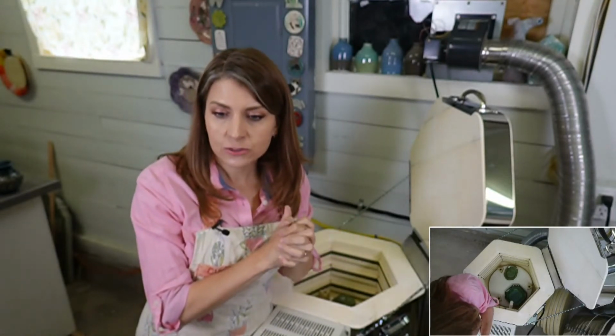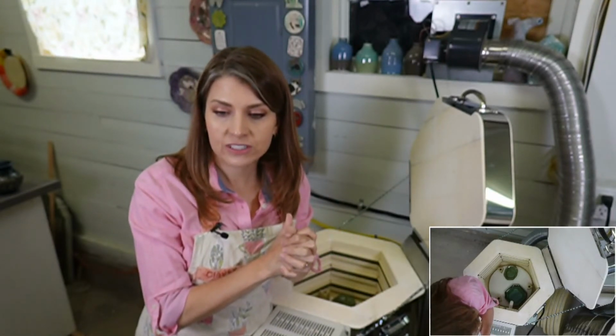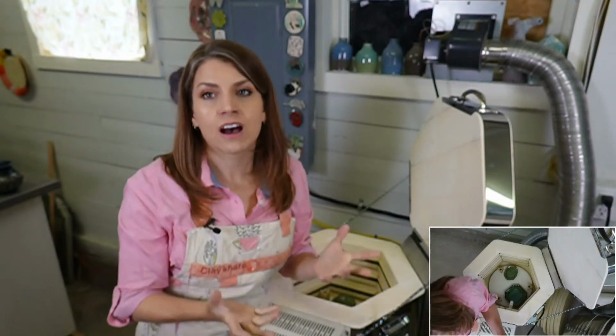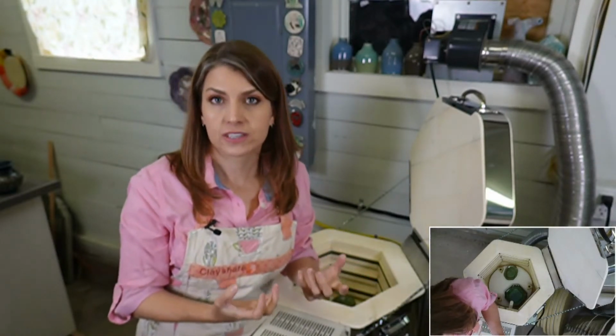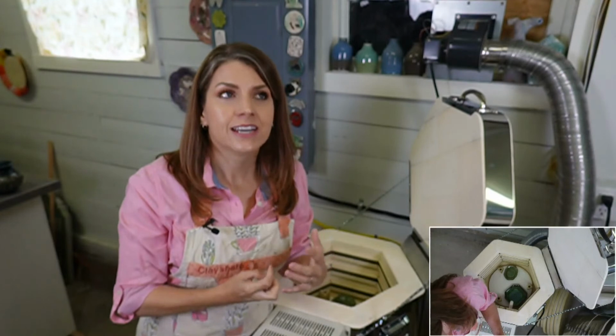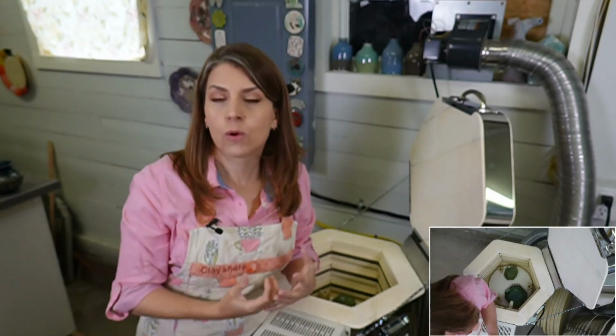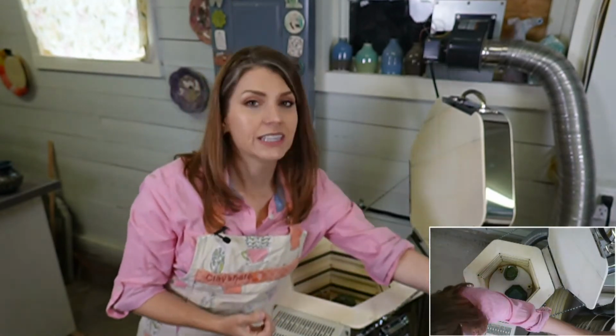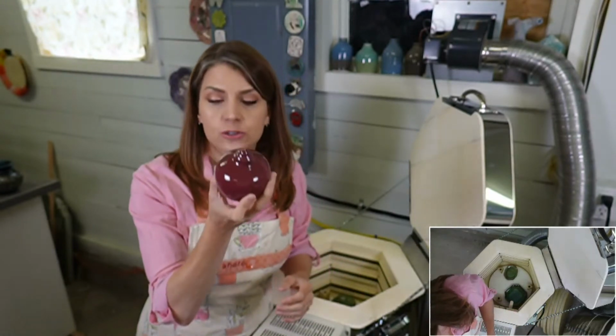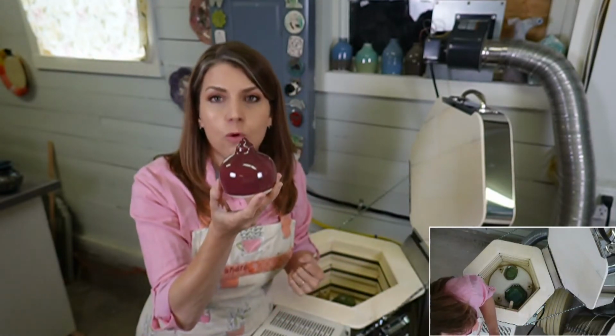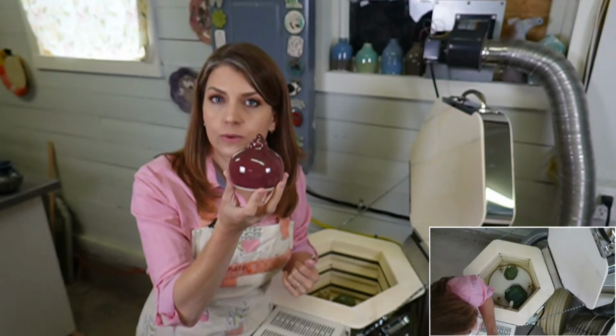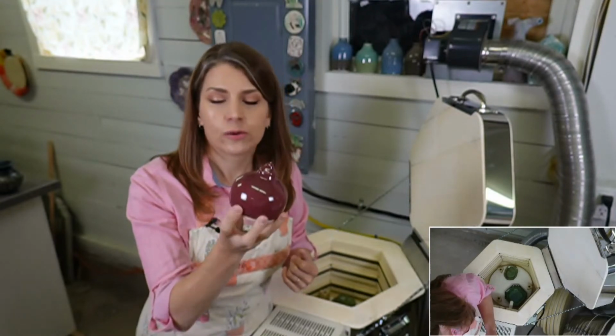So you only do low fire glazes, 05, 06. Can you use these glazes? They will not mature at 05, 06. They will be very matte and they might even flake off. They won't have bonded properly to the surface. You really need to take these up to cone... You could probably do 4. You could get away with cone 4 with this, but I wouldn't go much lower.